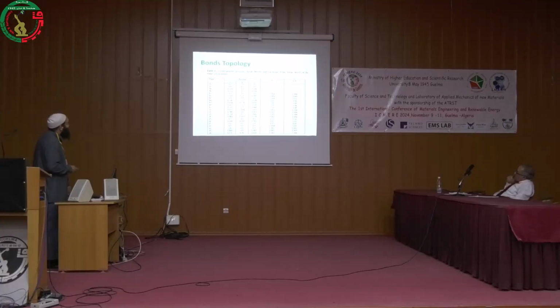As we can see here, the densities are small and positive, and the Laplacian is also positive. When we have a positive Laplacian, it's an ionic bond, and when it is negative, it is a covalent bond. Here we don't have negative values, which means that this compound has mostly an ionic to covalent nature. The bond between selenium atoms is in the center, and between selenium and titanium, and selenium and zirconium, they are closer to selenium and zirconium respectively.